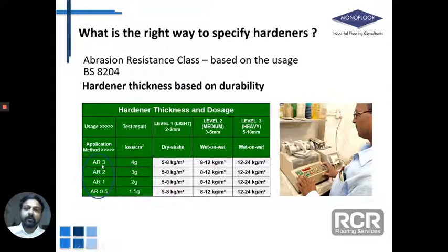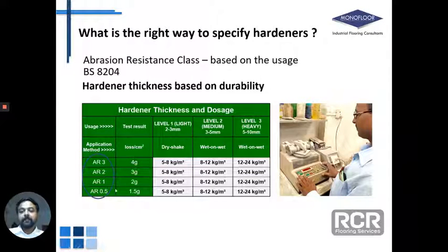Coming from the previous slide, you can see that if the aggregate in the hardener becomes harder and harder, the indentation that you can get is much lower. So with a standard test, if the indentation is low, it's classified as AR 0.5, and that's a better performing hardener. That's a more abrasion resistant hardener. So if you move from AR3 to say AR 0.5, you are increasing the grade of hardener, and you can choose different kinds of hardeners based on the class of hardener, and hence this forms the right specification for how we have to specify hardener based on the abrasion resistance, and this is the right way to specify hardener.